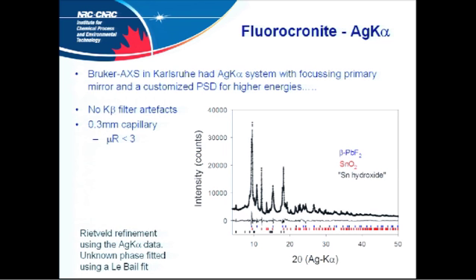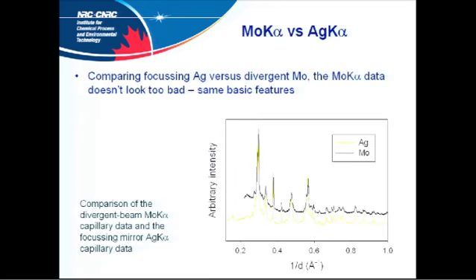A 0.3 millimeter capillary again. This time, a little rule of thumb: I like to see mu r, where mu is the linear absorption coefficient and r is the radius of the capillary, below 3, because a lot of absorption corrections can't really cope that well with highly absorbing data sets. So it's nice to get that down to a sensible value. It's multi-phase, but with modern software, you can actually deal with that. That's not a horrendous problem.